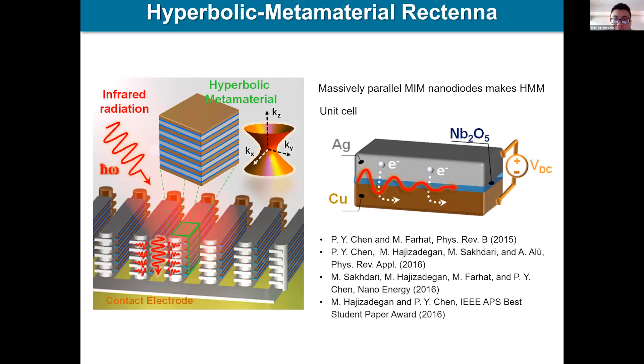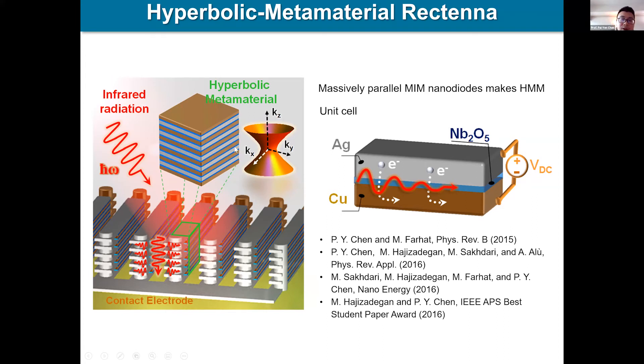To take a further step, we not only designed MIM nano-diode based nano-antennas, but also made them with hyperbolic metamaterial. Although our MIM device shows unique capability of ultra-fast and sub-band-gap operation, the nano-rectenna geometry may not be the most suitable structure. In order to boost the external conversion efficiency and bandwidth of operation, we propose an efficient design based on the hyperbolic metamaterial, which is made of cascaded dissimilar metals and ultra-thin Nb2O5 insulator in the middle.